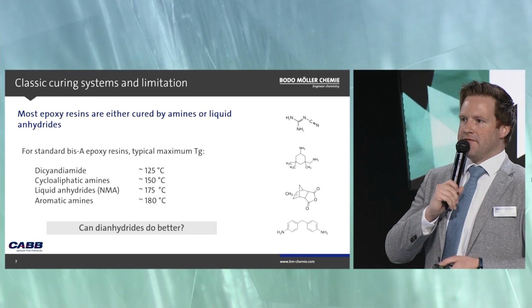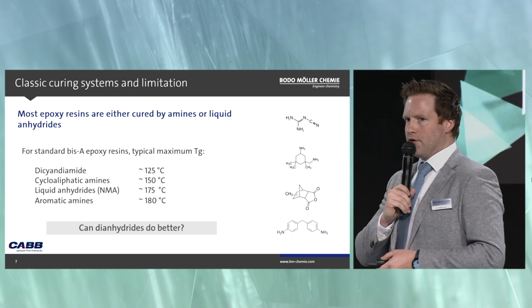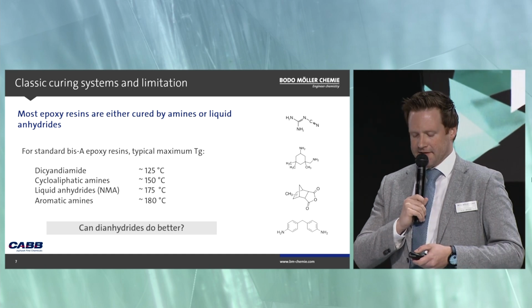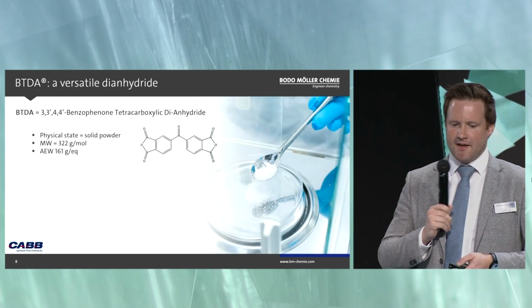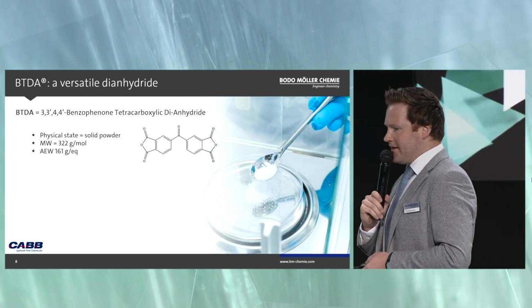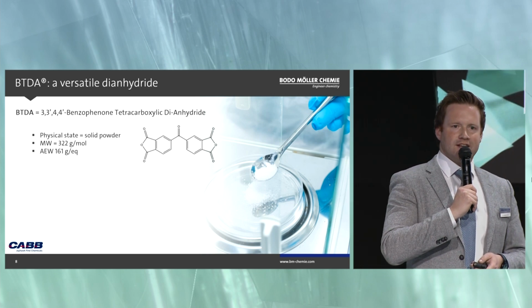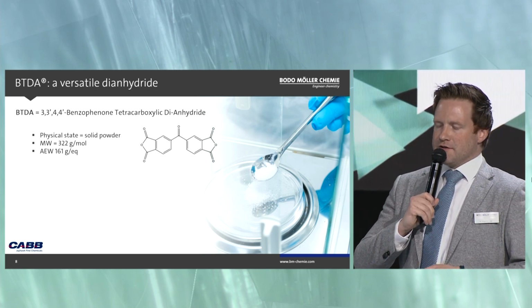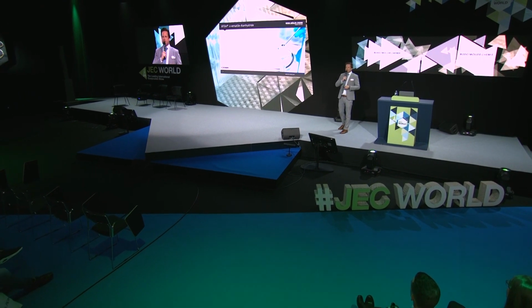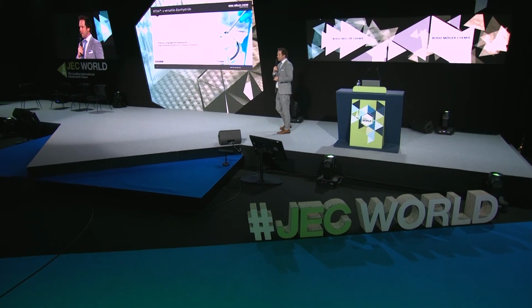Now the question is whether dianhydrides can do better when talking about mechanical properties, durability, and glass transition temperature. That's why I would like to introduce to you today BTDA, benzophenonetetracarboxylic dianhydride. We are talking about a solid powder, molecular weight of around 322 grams per mole, and an anhydride equivalent weight of 161 grams per equivalent. And this is an outstanding curative for epoxy resins. What you achieve is thermoset materials with very high temperature stability and also really good electrical insulation properties.